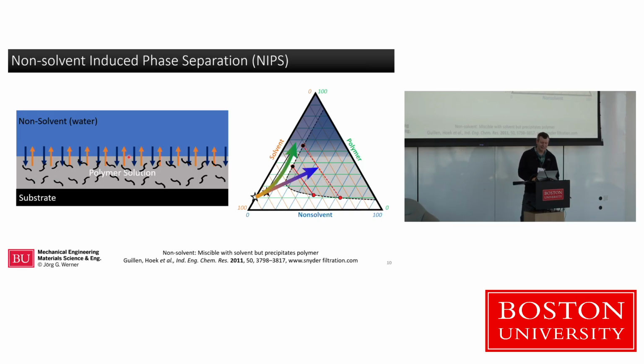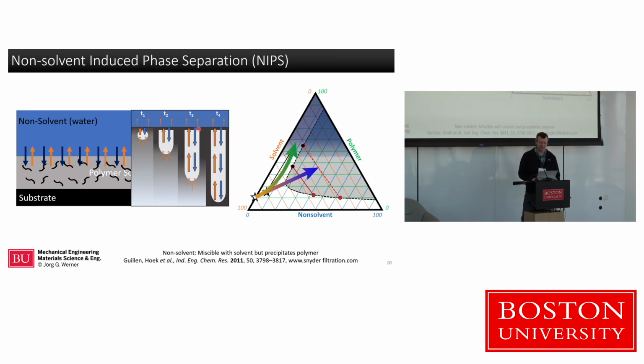Now, if you're using a solvent that by itself is miscible with water, but the polymer wants to precipitate, you get this phase separation. So this is the ternary phase diagram of the 3 components. You quench the overall system into a space where it's thermodynamically unstable. So you're causing phase separation, and that phase separation is between the non-solvent, often the water, as droplets inside that matrix of now a very high polymer concentration, gel and later solid, the more of the solvent it drains out.